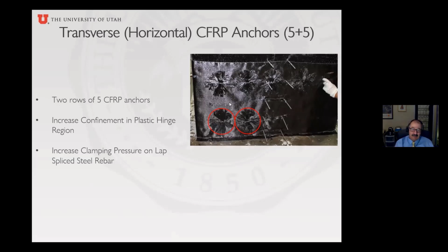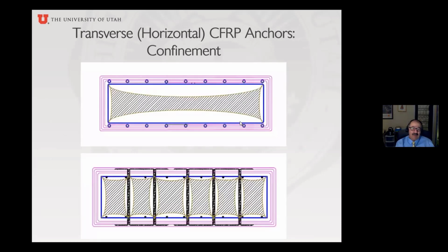Then there is a layer below, confining layer of carbon fiber, the anchors, and then there is one above. So we found out in previous work that if you sandwich the anchors, actually it makes them very strong and very hard to fail. So, I mean, these anchors help with confinement as well, because this is a very long wall. It's 4 feet long, and they increase the clamping pressure on the lap splice bars, and they also increase the confinement.